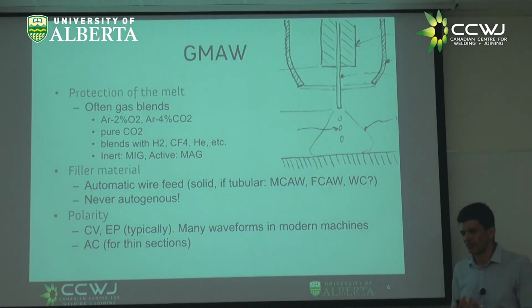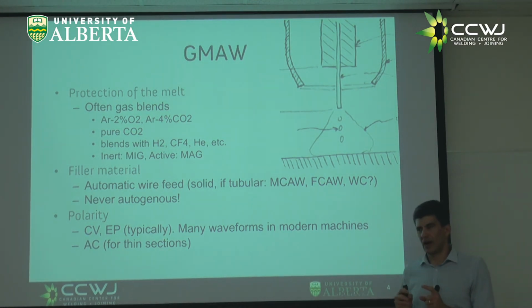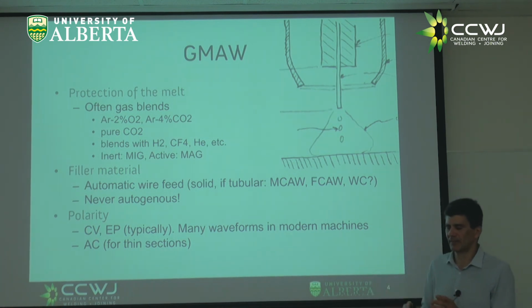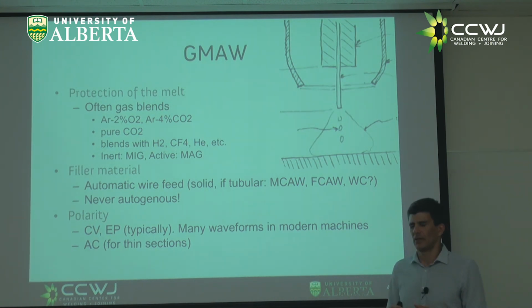Why would you have those mixtures? The reason is that the arc in tungsten is pretty well defined, because tungsten has special properties for the arc. It's called thermionic emission. Whatever it is, we'll discuss it later. But steel and aluminum don't have those things, so the arc is quite unstable. But if I have a little bit of oxidation, the arc stabilizes. And this is somewhat related to the issue of cleaning. I mentioned to you that when the plate is negative, we clean it, and we do that in aluminum. But in steel, when the electrode is negative, if I put a little bit of oxide, the arc gets stable.